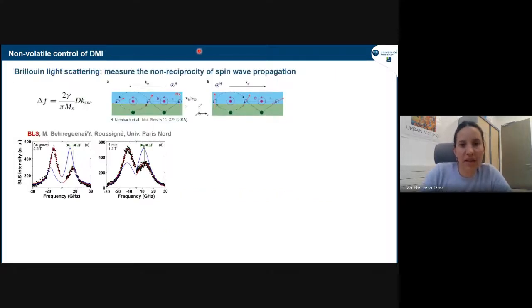I think this audience is very well aware of DMI, but I would just say very fast that the DMI is an antisymmetric exchange interaction, which is different from, for example, the Heisenberg exchange interaction, where you have all your spins aligned in one direction. Here the DMI is actually an interaction that would rather have the spins aligned perpendicular. So this favors non-collinear structures. So it's a magnetic order, but it's non-collinear. It can be, for example, helical structures, skyrmions, and it favors the appearance of Néel magnetic domain walls in perpendicular materials, which would normally have Bloch magnetic domain walls.